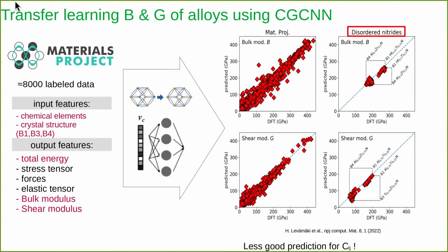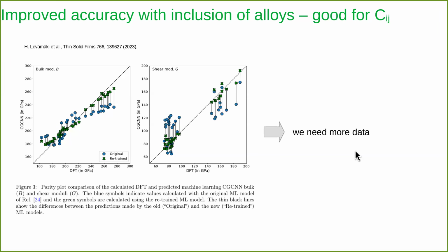Unfortunately, the pre-trained model performed less well for the Cij. So if we wanted to calculate or predict the elastic constants, that was not so good. But what we did, we retrained that model. Since we had more and more data in HADB, we added a certain part, fine-tuning our CGCNN model, and then you see here the results.